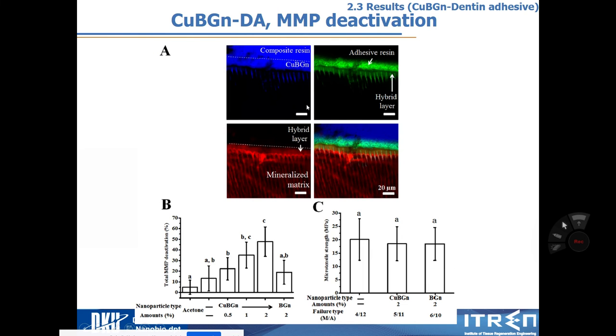And then this is the most important thing. From the total MMP, MMP is an enzyme from the dentinal fluid that degrades your adhesive resin. So the MMP is highly decreased in CUBGN. Inactivation is increased, which means that MMP is decreased. And then, from this decrease of MMP activity, micro tensile strength is maintained with CUBGN. When you look at the failure type, CUBGN is better than without nanoparticle.